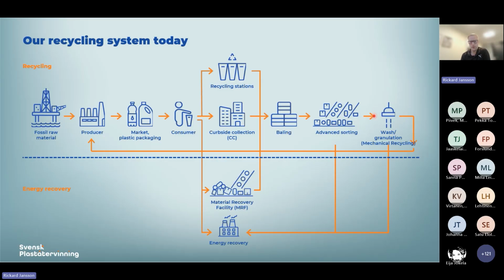But the majority of what we recycle today goes through mechanical recycling and will become a mono material in the end. We do get sorting rejects, and also in the mechanical recycling process you will end up with some rejected material. So in the sorting process, for example, if you have a multi-material where you have a laminated structure with different layers of different plastics, mechanical recycling will not be able to separate these different layers, and that means that if we would mechanically recycle it, it will end up as a low quality material,